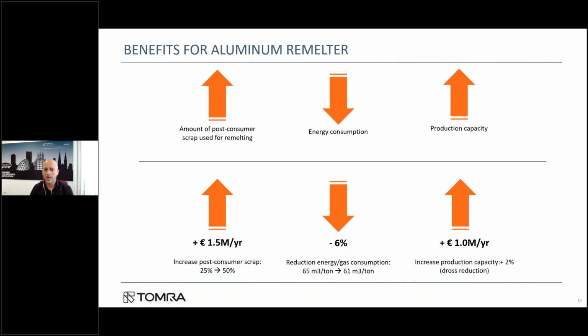The information at the bottom is data we received from one of our existing customers. So these numbers reflect their financial benefits as a remelter from the moment they started using scrap sorted by X-ray transmission compared to the situation before when they were using unsorted scrap. So they were able to double the amount of post-consumer scrap instead of using primary, which based on the price difference alone gave them approximately €1.5 million benefit per year. Then they were able to reduce the gas consumption by 6%. And finally, the production capacity was increased by 2%, which led to roughly €1 million benefit annually. So for them, in addition to supplying greener aluminum with higher recycled content, it's also clear that there are commercial and operational benefits as well.